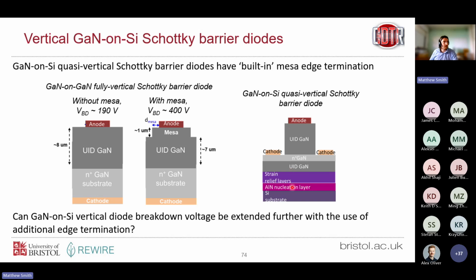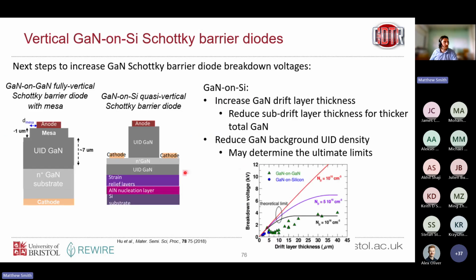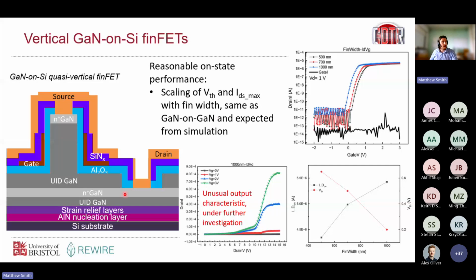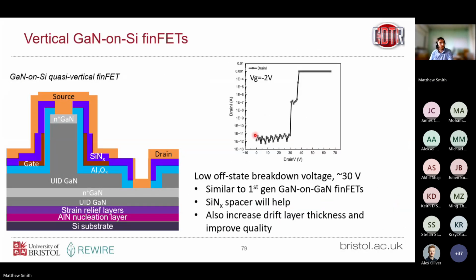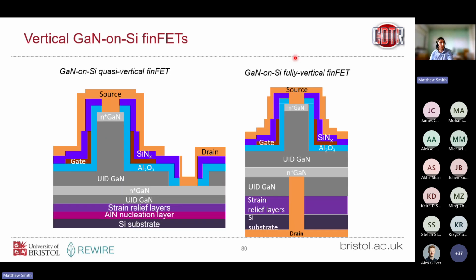Okay, so we want to move eventually to fully vertical devices, skipping through here just for time. We did make FinFET based on the GaN on silicon platform, quasi-vertical, so again, putting the drain contact to the side rather than etching all the way through. Reasonable on-state performance, very low breakdown voltage. We think we might know the reasons for that. This was done actually before the GaN on GaN FinFET work I showed earlier. So we think our next generation of these GaN on silicon FinFETs should be much higher breakdown voltage. But yeah, they were breaking down at kind of 30 volts initially.